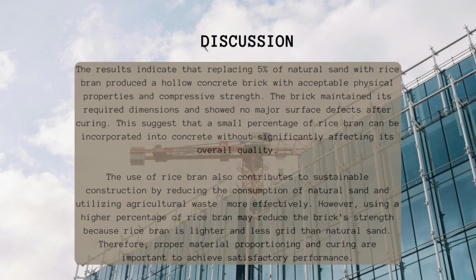Next, based on our experiment, replacing 5% of natural sand with rice bran produced a hollow concrete brick with acceptable quality. The brick maintained its standard dimensions and had a good surface condition without major cracks or defects after curing. The compressive strength showed that the brick was still able to withstand the applied load, which means that a small amount of rice bran can be used without significantly reducing its performance.